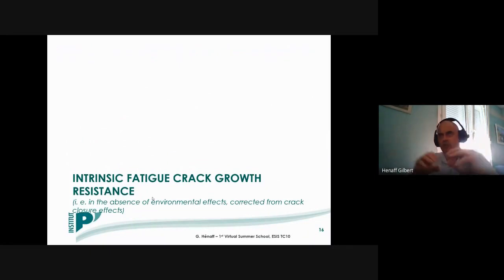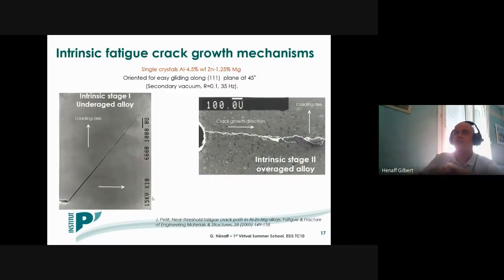This intrinsic fatigue crack growth resistance has to be determined in a perfectly inert environment. So you have to limit as far as possible the presence of water vapor. And also, as I explained before, by taking into account the crack closure effect that can reduce the effective stress intensity factor range at the crack tip. So when doing that, you can observe different types of crack propagation mode.